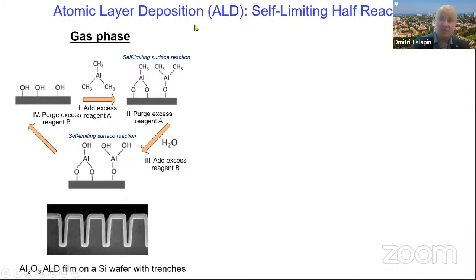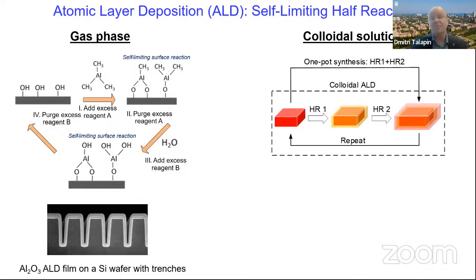In semiconductor technology, we routinely use a process called atomic layer deposition, where you can grow conformal layers of, for example, oxides, and that is used in transistors to grow so-called gate dielectric layers. And the way you can grow this from gas phase in a very conformal way is to split the reaction into two complementary half reactions, where each reaction is self-limiting. So you grow one monolayer, then another monolayer, then yet another monolayer. And we developed an analog of this process that can be done in solution, not in gas phase.